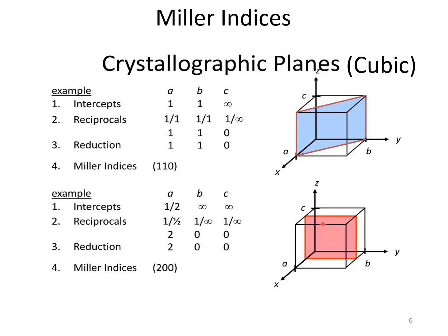In this particular case, the intercepts are at 1 on x, 1 on y, and basically 0 on c, which means really an infinite intercept. It intersects at infinity, but in terms of the lattice parameter, you can just see it by inspection. One knows that that's a 1, 1, 0, because it doesn't intersect with the c-axis.